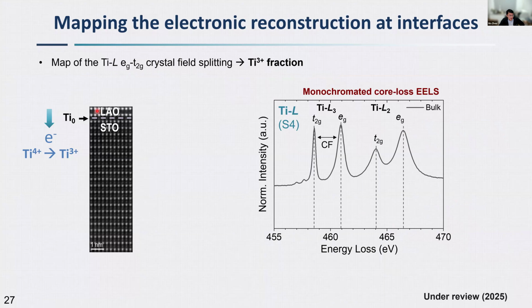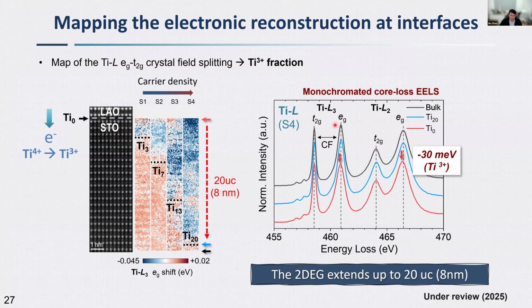In this case, because lanthanum transfers electrons to the STO layer, the titanium oxide layer, it will partially reduce the titanium 4+. We can see this actually from the titanium L edge. And you can see that going from the bulk all the way to the interface, there is a very small shift, about 30 millielectron volts, on the EG energy level.